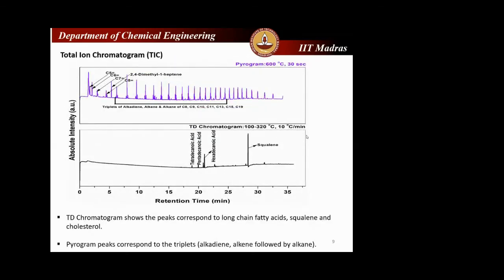After the TG and FTIR analysis, I subjected the samples to PyGCMS using a multi-shot Frontier pyrolyzer coupled with GC and an MS quadrupole detector. I took a sample amount within the 100 to 200 microgram range. With that same sample you can do two analyses. In the first program, you can do thermal desorption, and after thermal desorption the same sample is dropped to the pyrolysis region. This is the benefit of the double shot. This is called the thermal desorption range.